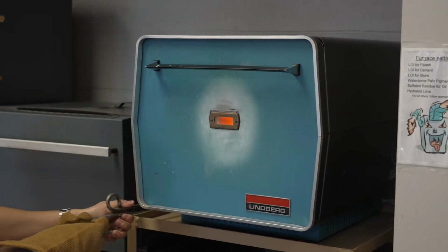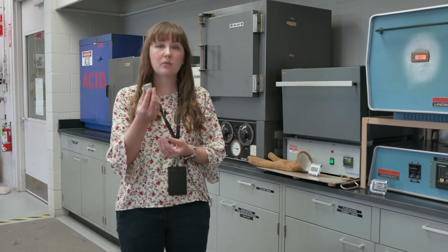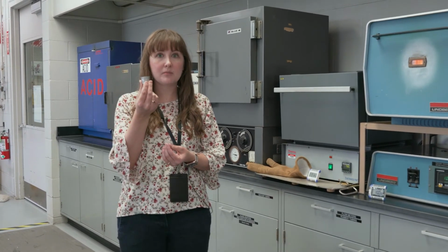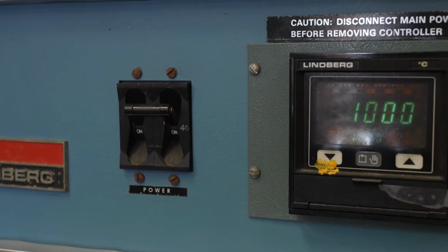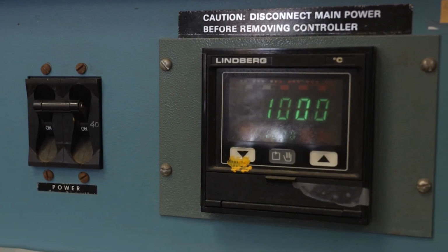For cement, we do a loss on ignition test, and this measures the amount of moisture and carbon dioxide that's in the cement. And we do that by measuring 1 gram of sample in a platinum crucible, and we put it in a muffle furnace at 1,000 degrees Celsius for 1 hour.